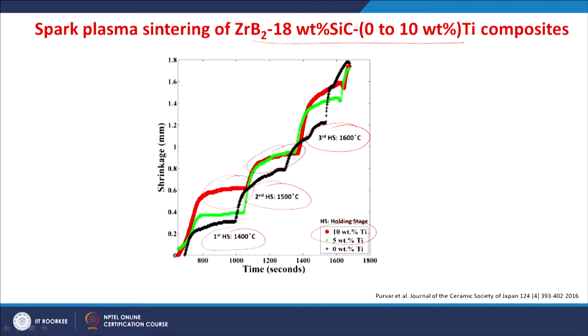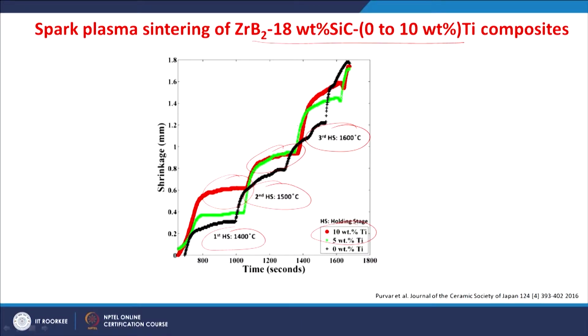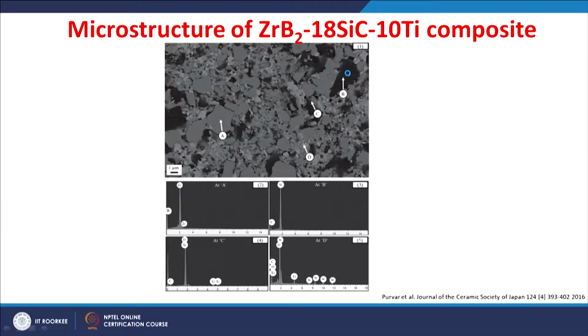So, this helps us. This indicates the addition of titanium in the composite powder mixture of zirconium diboride and silicon carbide will improve the densification, or will densify the material at lower stages of sintering itself. The shrinkage further increased to the next stage, and then maximum shrinkage was obtained in the third stage of sintering. The microstructure of these composites particularly show zirconium diboride grains and silicon carbide particles,